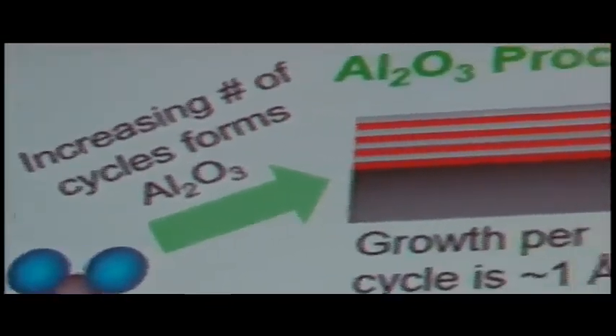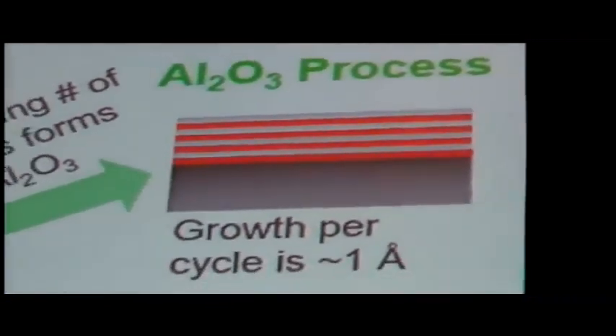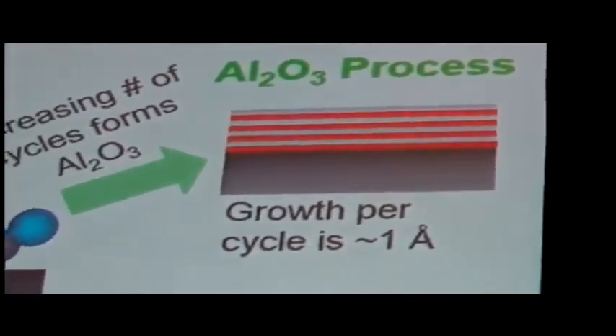In the case of the alumina, we grow about an angstrom at a time. So for making something like 10 angstrom onto the surface, we take at least 10 cycles of aluminum through there. And you'll see the use of the word cycles throughout the talk I'm giving today. That basically is this entire cycle that you see going on here. So, the other nice thing about ALD is it's not a line of sight process.